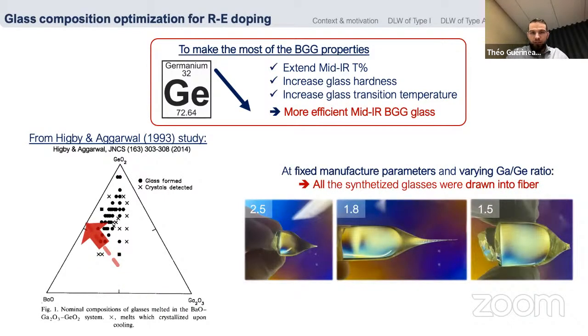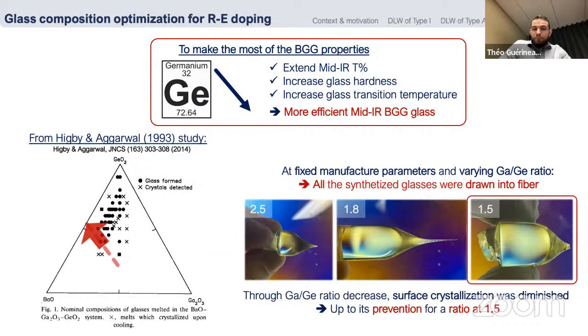We worked with 3 ratios, and we fixed the manufacturing parameters for the manufacture of our preform. In all the cases, at first we were able to draw the fiber, but after tens of meters, we observe a degradation of the preform, as you can see here with the crystallization of our neck downs. For ratios of 2.5 and 1.8, we still have the formation of the crystallization effect, but at 1.5, we don't have this crystallization. By keeping the same manufacturing parameters, we were able to prevent, in this case, the appearance of these crystals.